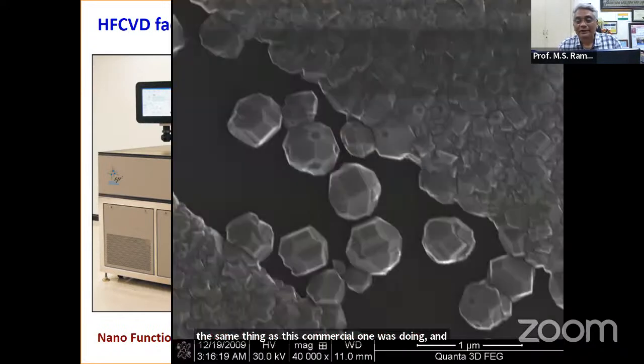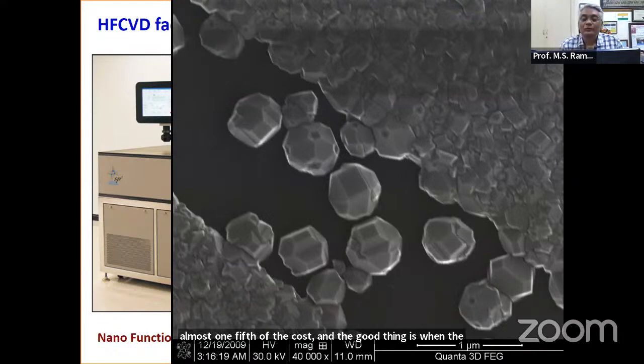Just to show that, this is a commercial setup we have now. We've got an indigenous setup built in India to do the same thing as this commercial one was doing, at almost 1/5th of the cost. And the good thing is when the crystallite size is very small, you even start seeing a 5-fold symmetry.